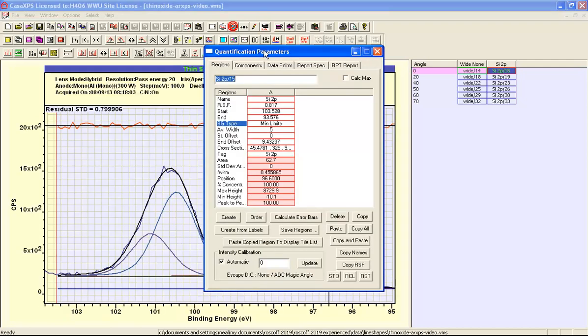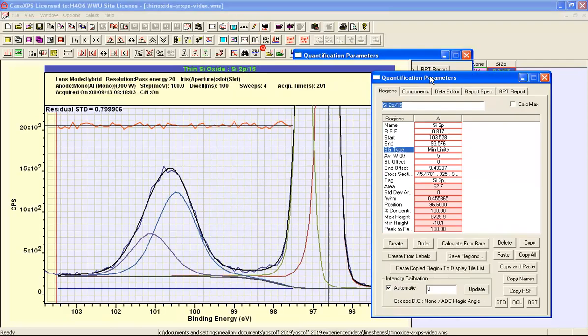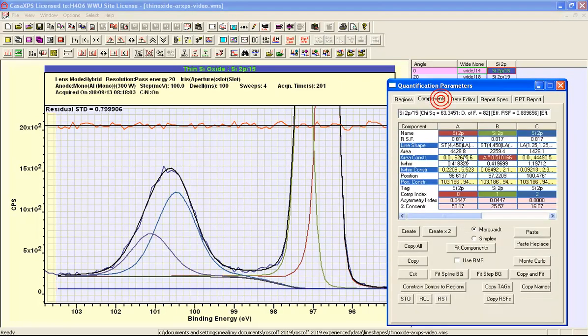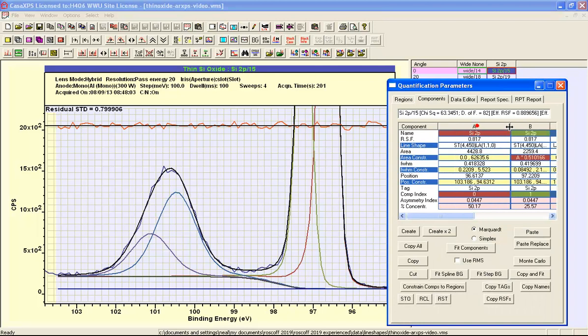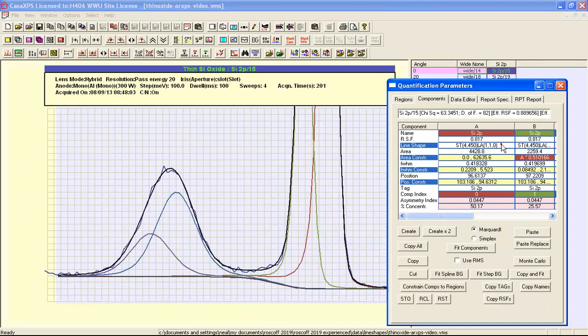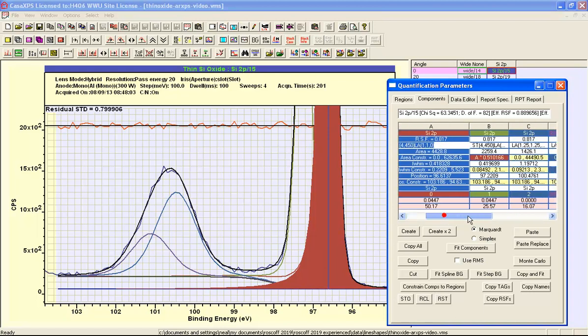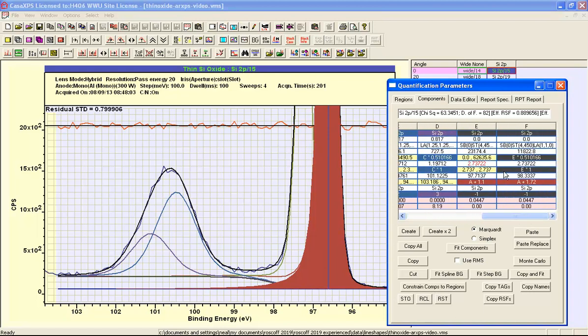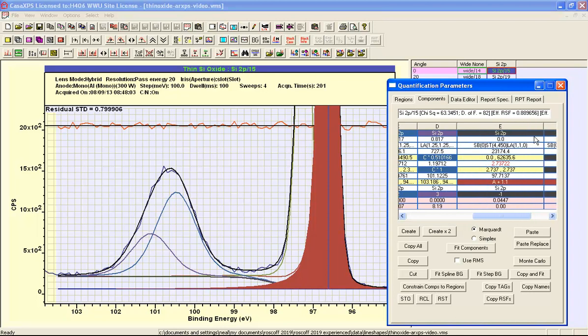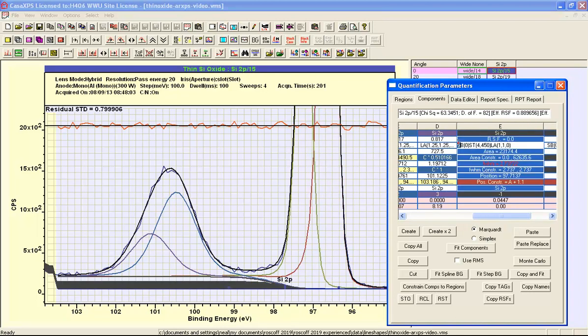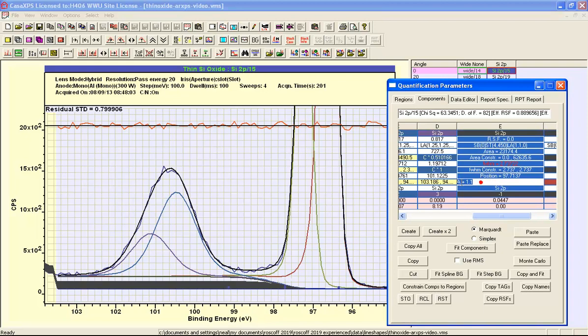The definition of the background components within this peak model are based on the line shape that has been used to model the asymmetry within these elemental peaks. And then the same line shape is presented here. So this prefix indicates that the line shape that follows should be integrated to form a shape which can then be fitted as part of this exercise.